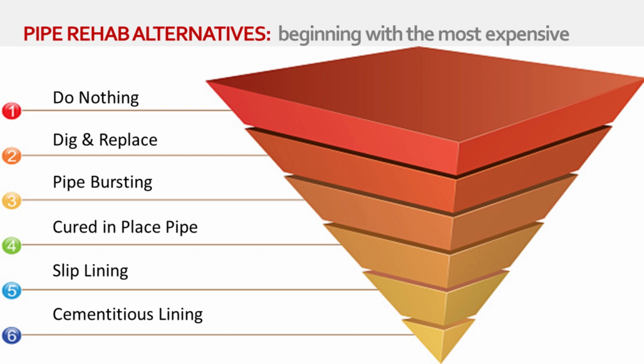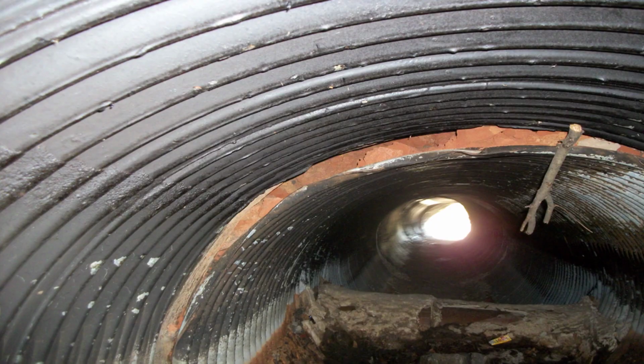And then, of course, the last would be cementitious lining, and that is often the most economical that we find, and it typically requires a much smaller work area or footprint. And I want to jump into a profile of a project we did in Warner Robins, Georgia. This is a 60-inch corrugated metal pipe, and from the picture there, you can see an open joint. This was under a busy 4-lane city street that had a lot of school bus traffic. Public Works had actually inspected this pipe and saw that the invert was rusted, and they could see an open joint by just looking down the pipe.